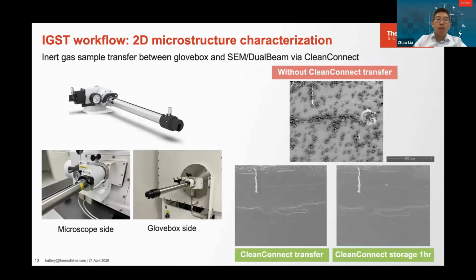The first workflow is a 2D microstructure characterization, which means you directly transfer the sample from the glove box to the dual beam to do the SEM imaging characterization. The key component that enables this workflow is a device called Clean Connect. As you can see on the left is a transfer unit that has a capsule that is able to store the sample. The transfer unit is able to attach to both the microscope side and the glove box side.